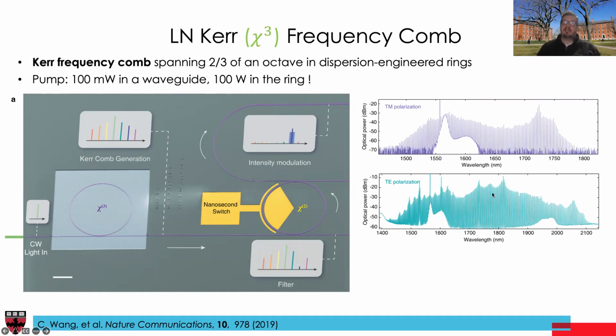For the experts, these combs were actually not mode locked, and these additional peaks correspond to Raman lines, which we also studied, and I'm not referencing that work here. But basically, because of this Raman scattering process in a crystalline material like lithium niobate, it turns out these combs were not locked, which is a problem for applications.